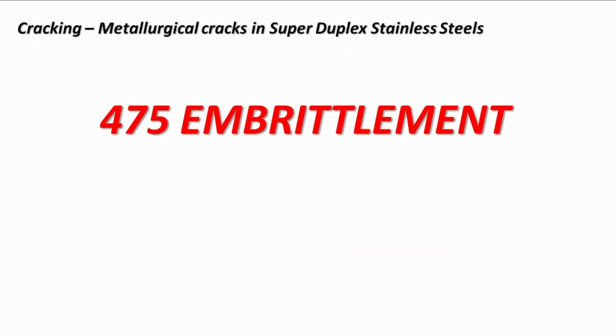We all know duplex stainless steel is susceptible to sigma cracking, but that is not the whole fact. Sigma phase is one of the phases that forms at high temperature, but there is another phase forming at 475 degrees Celsius, called alpha prime phase. In a steel foundry we weld the material to do repair work, or during gouging operations we expose the material to some heat. Whenever the material is exposed to 400 degrees Celsius and above, there is a chance for formation of alpha prime phase. That will create 475 embrittlement in the material, and at high temperature we will have sigma phase cracking.